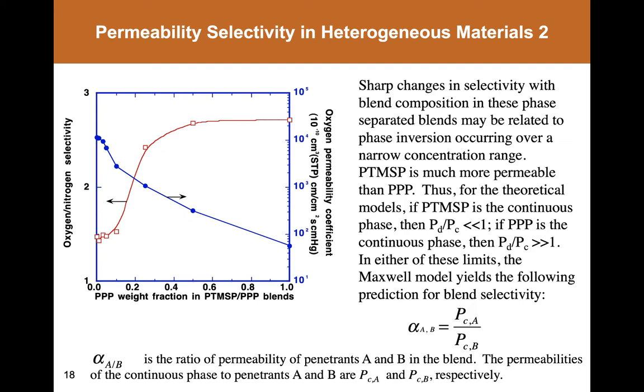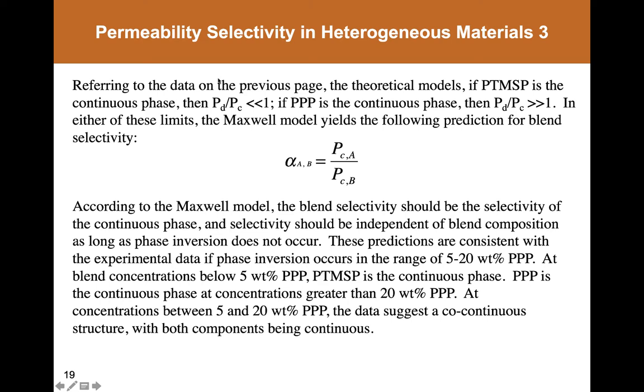Materials going, in this case, from being continuous in PTMSP to being continuous in polyphenylpropyne. The point at which this occurs in terms of composition, this phase inversion, can depend on processing history, the nature of the polymers, and many other factors. Now the data are consistent with there being a phase inversion in the range of about, in this particular case, about 5 to 20 weight percent polyphenylpropyne, and